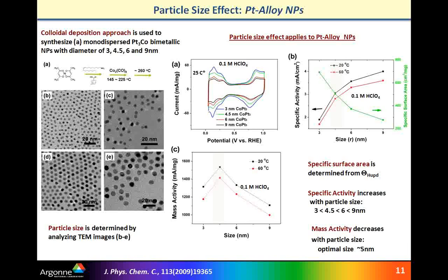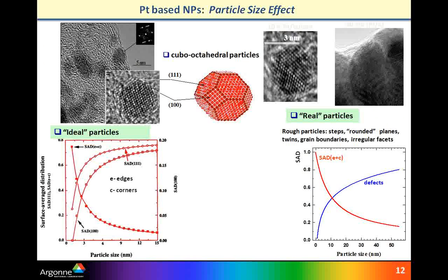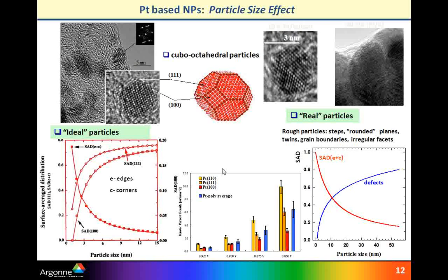And we were able to see that in terms of specific and mass activity, there is a particle size effect, and the sweet spot in terms of optimizing specific and mass activity would be somewhere around 5 nanometers. So from there, it would be important to recall some basics about the origin of the particle size effect and why something which is supposed to be well established in the field is still subject of big debate. So here is a summary of literature data and our own data and our own explanation. And it's very obvious that small particles are very rich in edge and corner sites, while with particle size, as one can see, those sites are diminishing, and therefore the contribution of one-one-one facets is getting more pronounced.